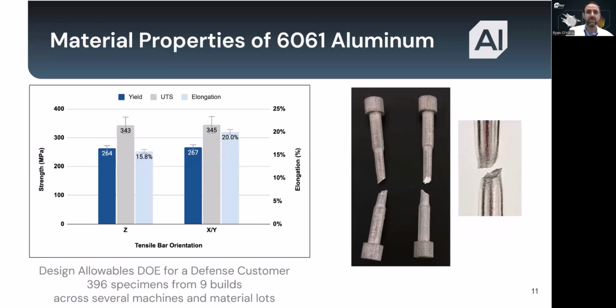What you see here are tensile tests from an initial qualification program we ran for a defense customer across 396 specimens from 9 separate builds, tested in both the Z and X and Y orientations. Our material demonstrated properties that are fully within the expected range for wrought 6061 in a T6 condition. Specifically, we see yield strengths in the 260 megapascal range, ultimate tensile strength above 340 megapascals, and elongation between 15 and 20%. The important takeaway is not just the numbers, it's consistency. Multiple builds, different machines, and varied material lots all converged on stable, reliable results.